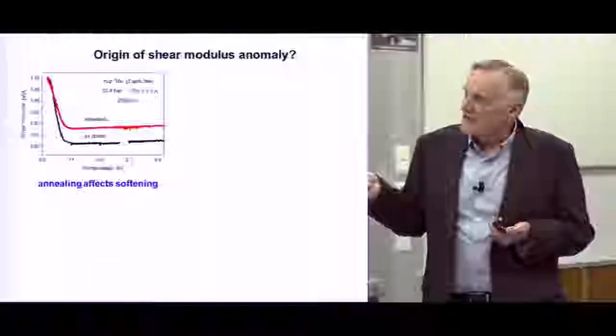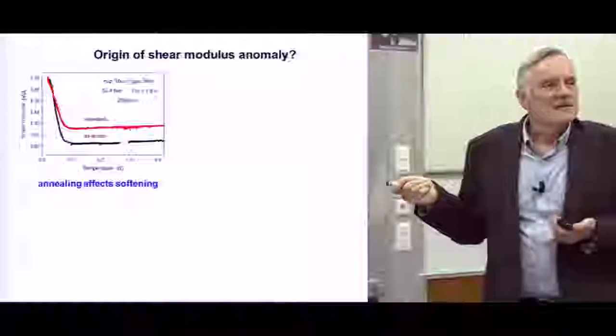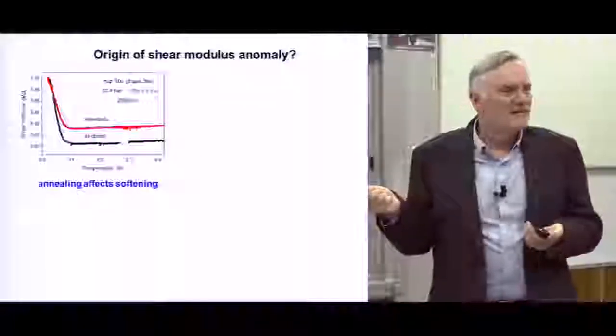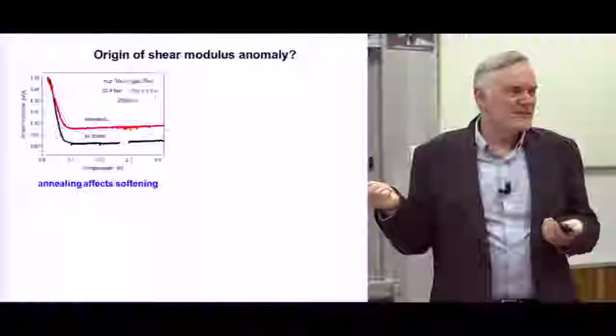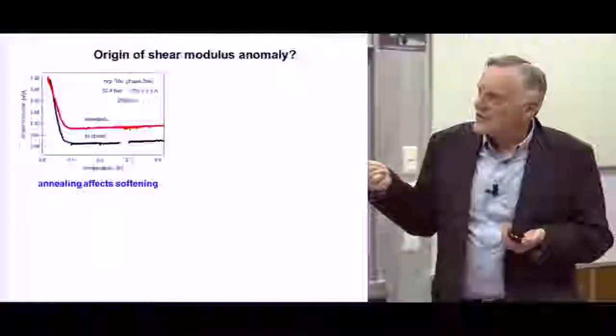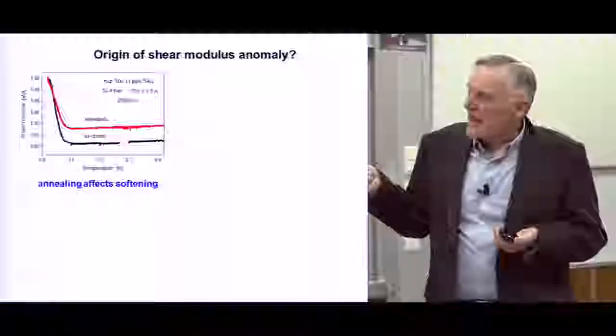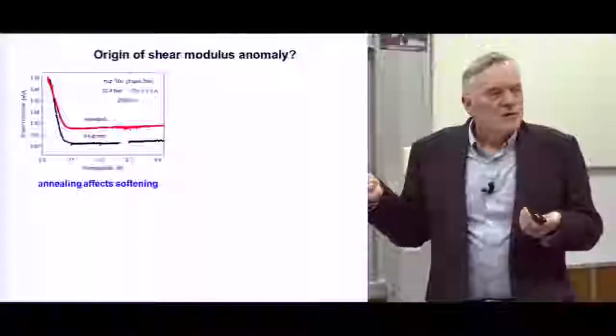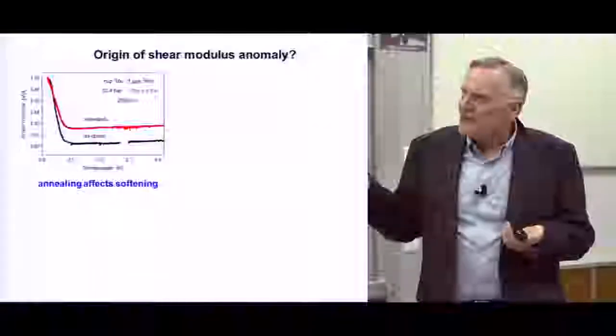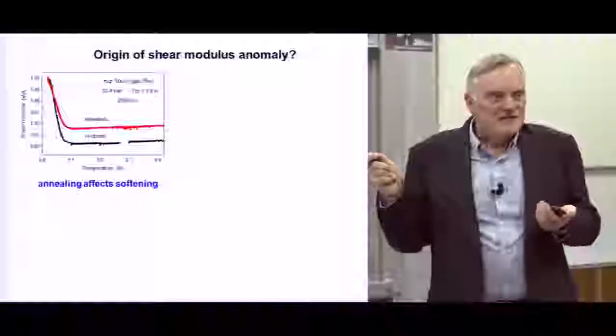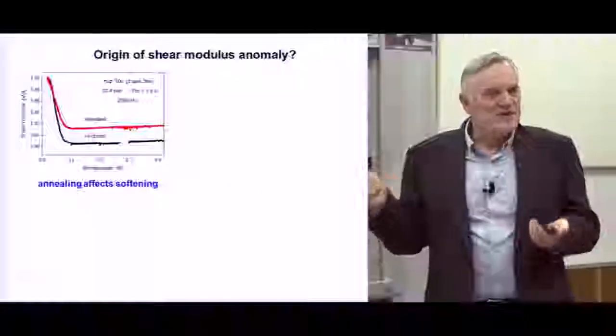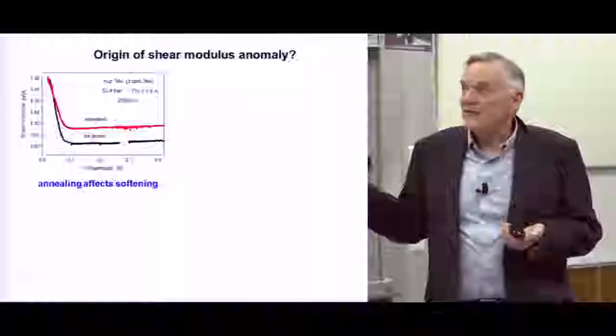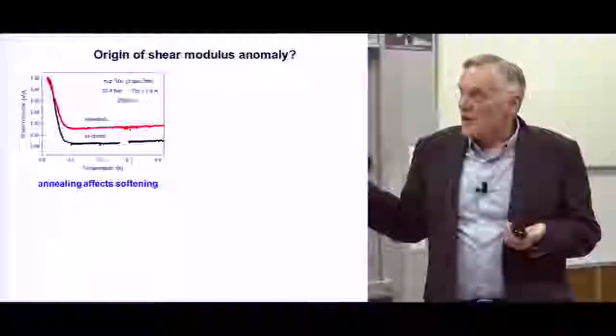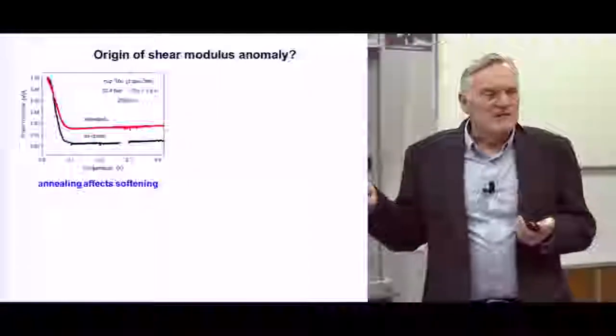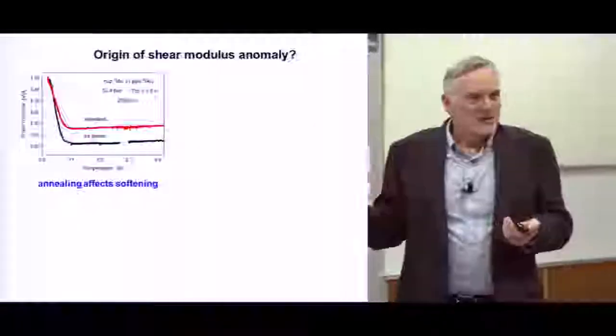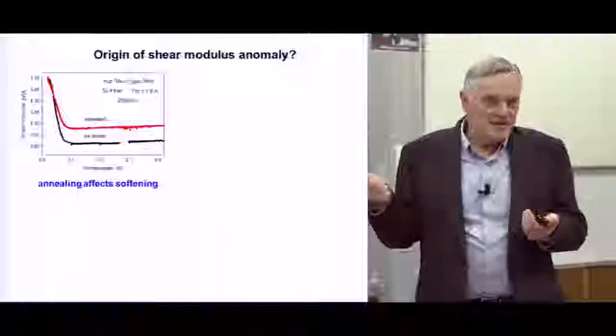So here's one thing that is suspicious if you think it's a supersolid, which is that annealing the crystal makes the effect go away, which suggests it's something to do with defects. And the other thing that you should notice from this is the before and after. The black is the shear modulus as a function of temperature, when you first grew a crystal, then you anneal it and measure it. What you find is at low temperature, it's in its intrinsic state. It doesn't make any difference. It's in its intrinsic stiff, real state. It's not actually stiffening, it's softening. This is the perfect crystal, and as you warm, it gets softer, and how much softer it gets is not as much once you've annealed it. So you have to turn around and think this is a softening effect due to something at higher temperature, not a stiffening at low temperature.